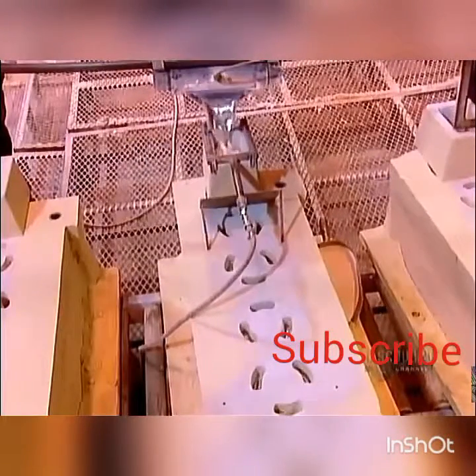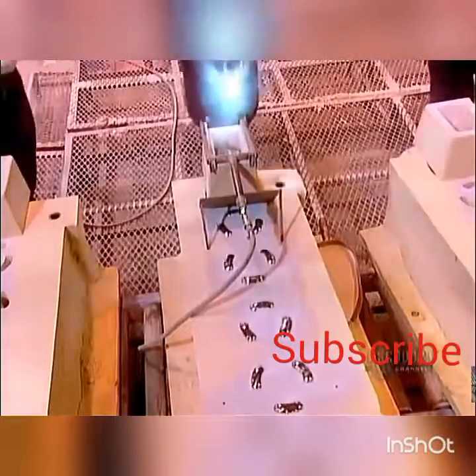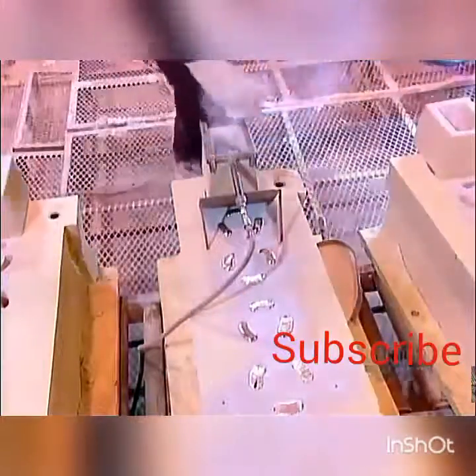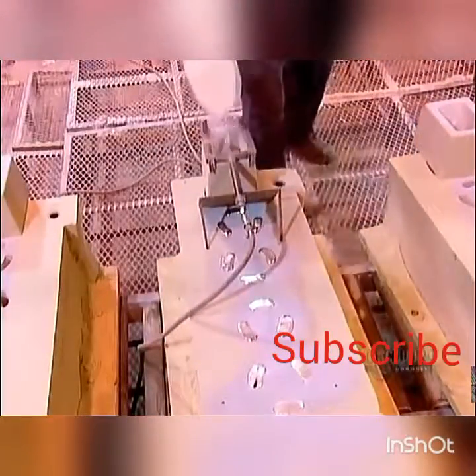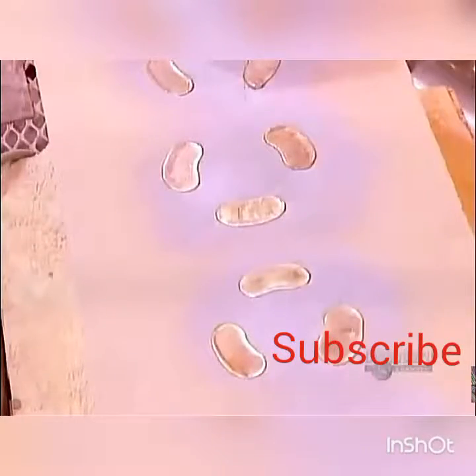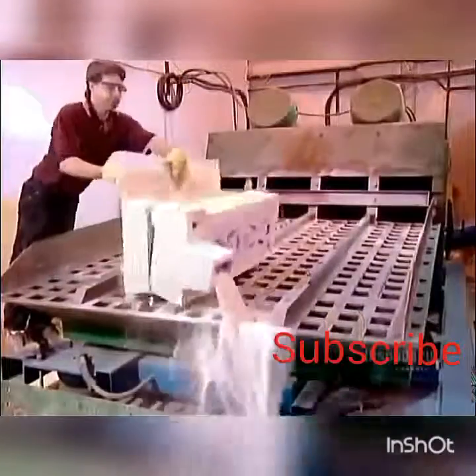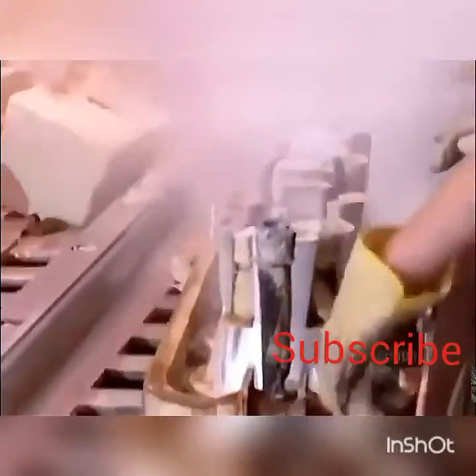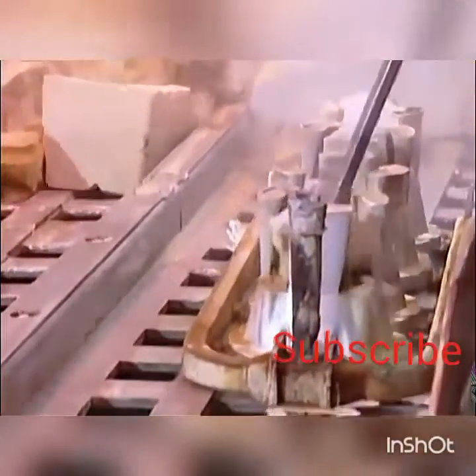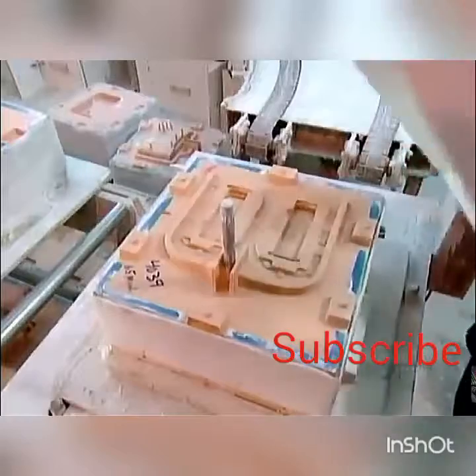Now they can finally cast the part. They carefully pour in the molten metal, in this case magnesium, heated to about 700 degrees Celsius. They block the hole with sand to prevent the metal from reacting to the air. The metal takes about 10 to 20 minutes to harden depending on the size of the mold. They crack the mold open on a vibrating conveyor.